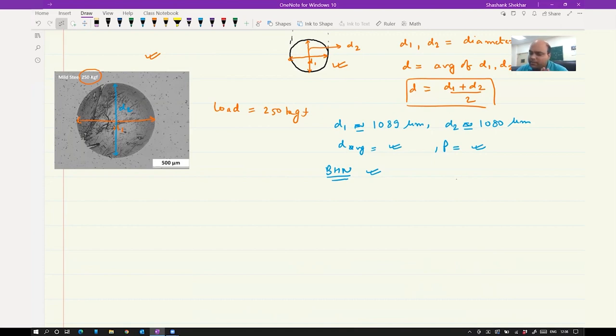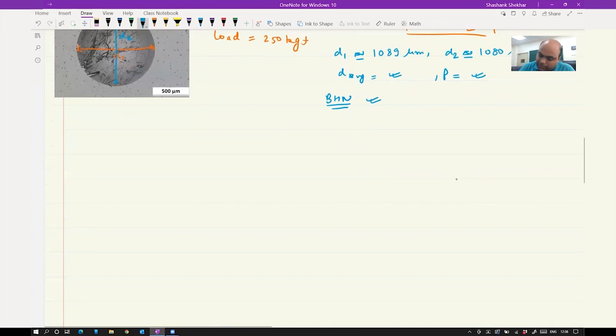That is point number one. In all the hardness tests, whether it is Brinell, Vickers, or Rockwell, your surface has to be smooth and polished. Basically, when you want to do any hardness test, you first polish your sample using a conventional metallography technique, and then use one of these three indentation methods depending upon your material, and then you can calculate the hardness value. So the first disadvantage is that it is not reliable at high hardness values, say greater than 400 or so. The reason is that your steel ball itself will start deforming. That is point number one.